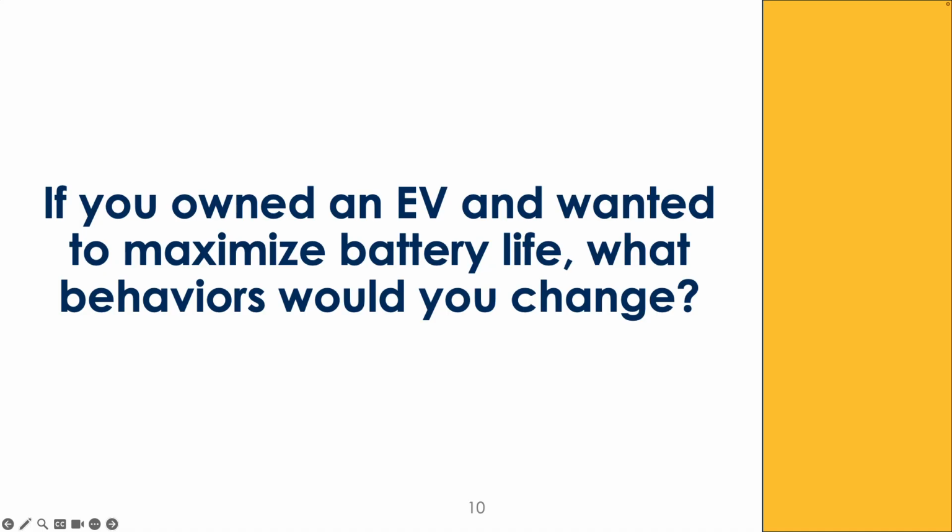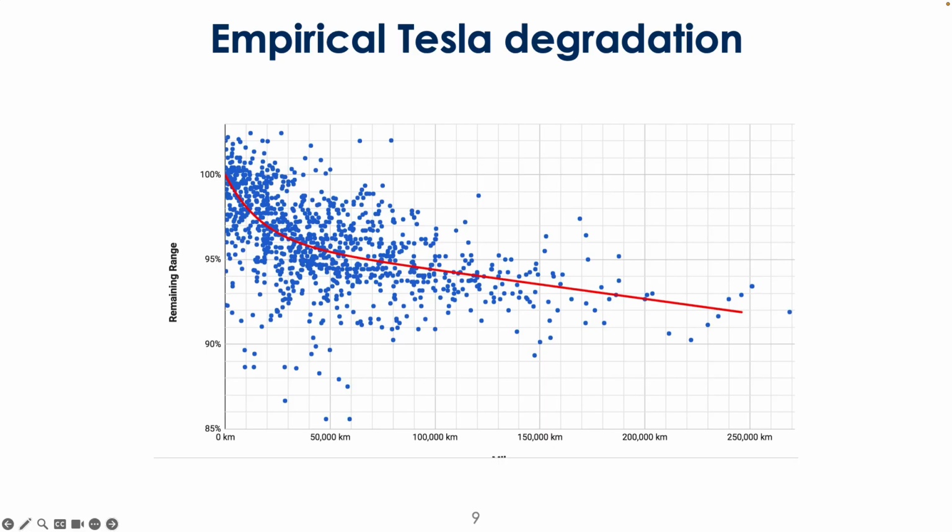That was actually a really big one that a lot of folks wondered about. Slamming a lot of electricity into your vehicle at high power, we would assume would degrade it faster. In principle, it should. Although it is kind of interesting, looking at this particular data set, it was pretty difficult to find a correlation between the speeds that people were charging and whether it was degrading faster.